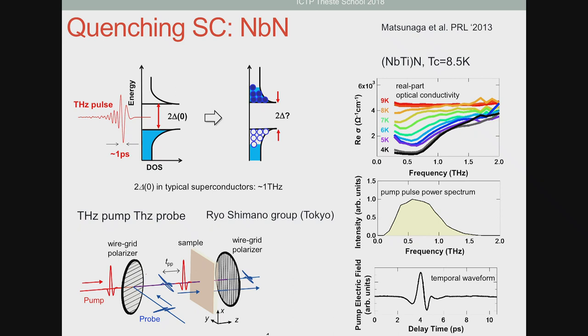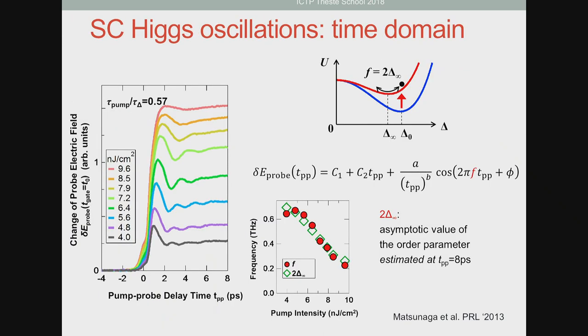What you are going to do is pump your system with this, and then see its evolution with time by sending another probe pulse, also in the terahertz range, to probe the dynamics of your superconducting gap. These are the measurements that were performed. This is the transmitted electric field in the terahertz range. Remember that in a BCS superconductor, if you are shining light at an energy below 2 delta, there is no transmission. So if you have a reduction of superfluid density or a reduction of 2 delta, you are going to have a modulation of your transmission, and this is what is observed here.